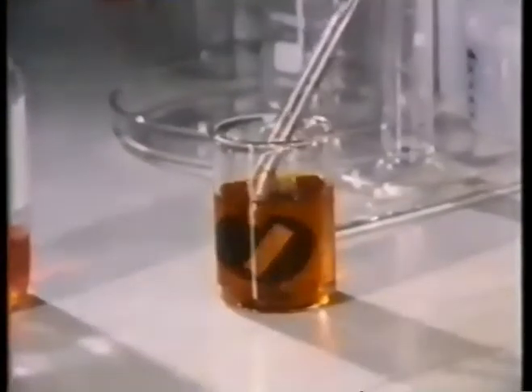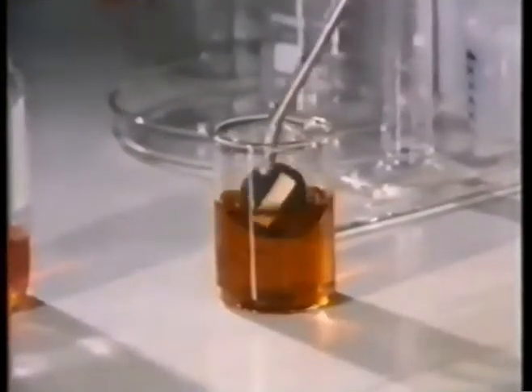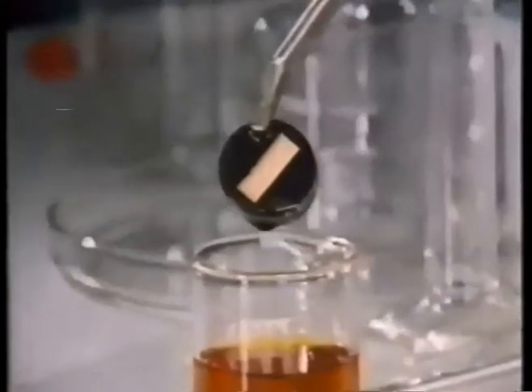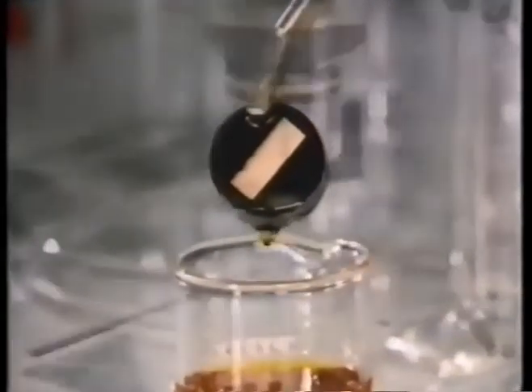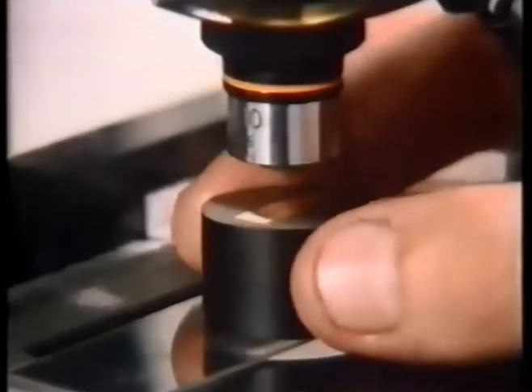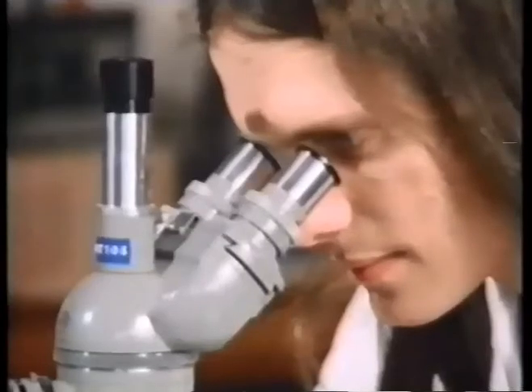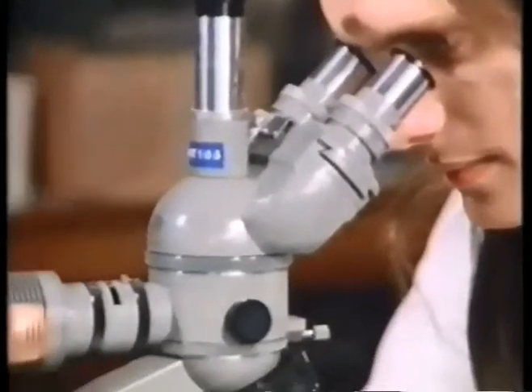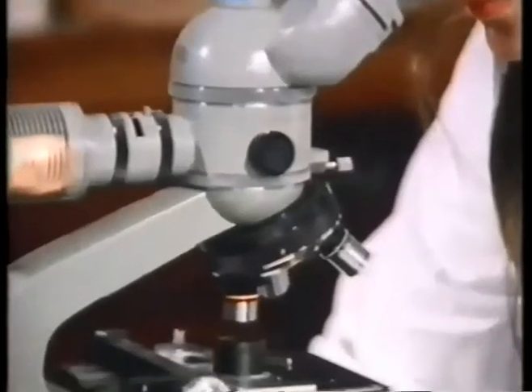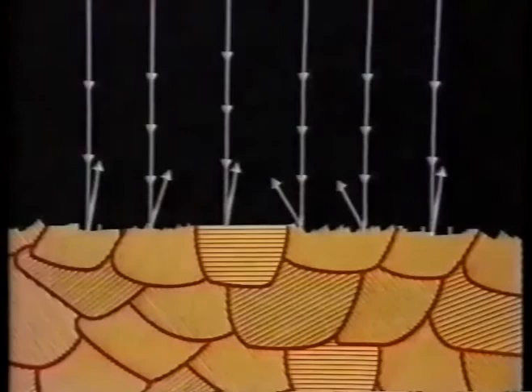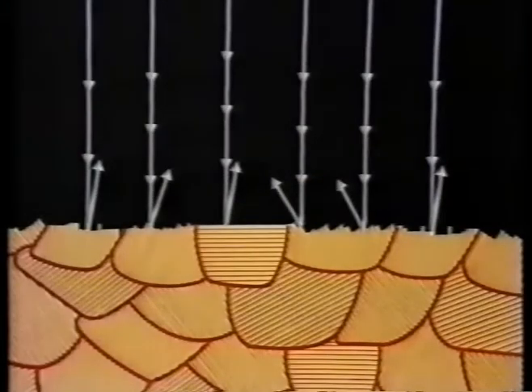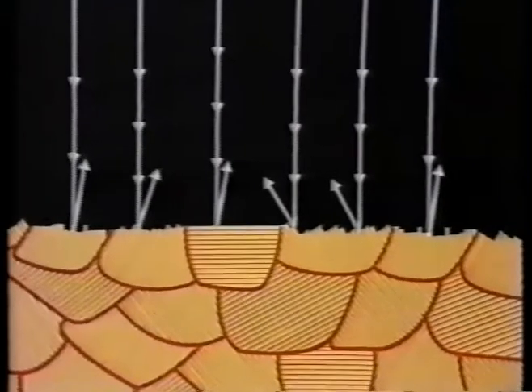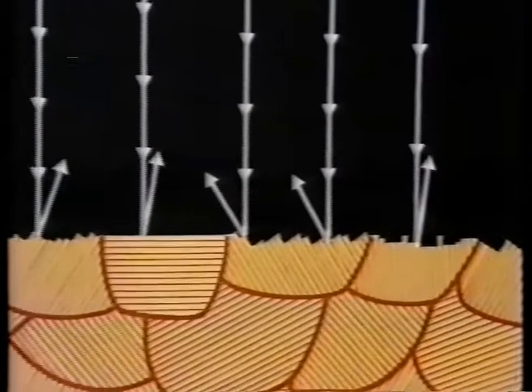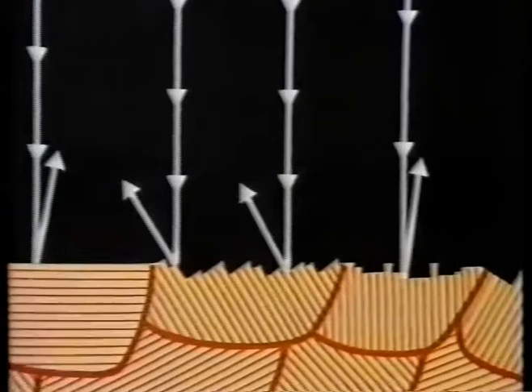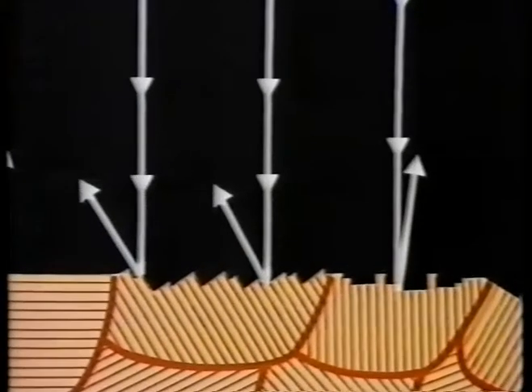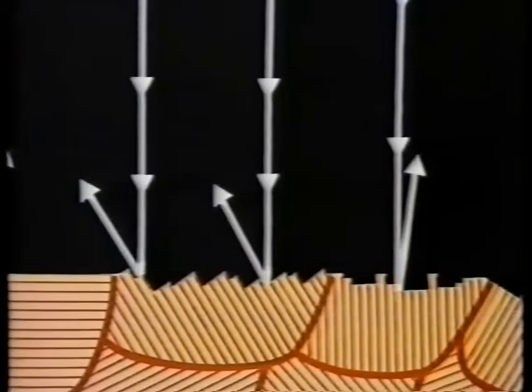In order to get more information from the optical microscope, it's usually necessary to etch the specimen, and this uses liquids which attack the metal surface at rates which depend upon the chemical composition of the surface and also upon the orientation of the grains with respect to the surface. Here's a schematic view of etched grains in a sample. In this way, it's possible to highlight different grains within the sample and local changes in chemical composition, since the attacked surface reflects the incident light in different ways.